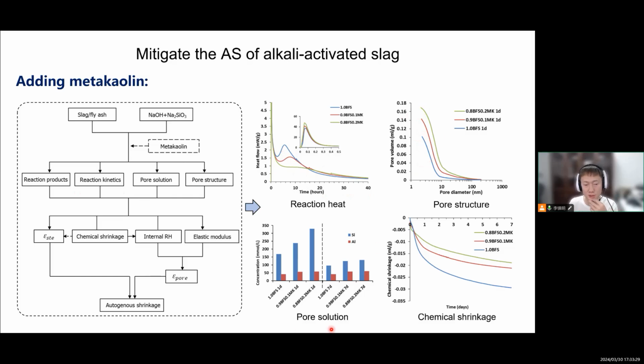And from the pore solution analysis, we can see there are indeed more silicate and more alumina there. And the early age chemical shrinkage is actually increased because the metakaolin is very reactive itself. So it dissolves even faster than the slag. So it contributes to a large initial chemical shrinkage due to the dissolution.